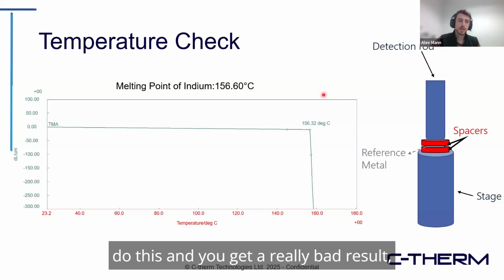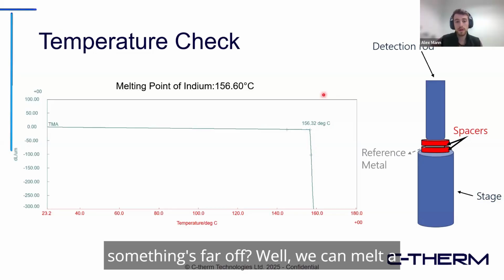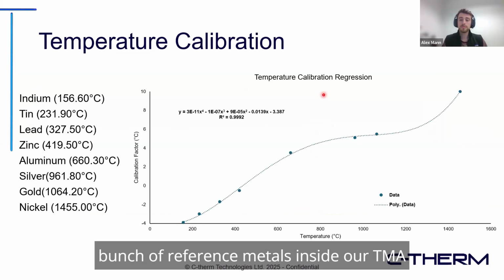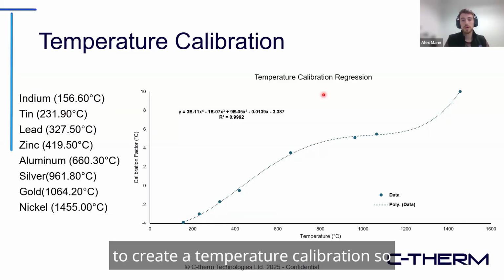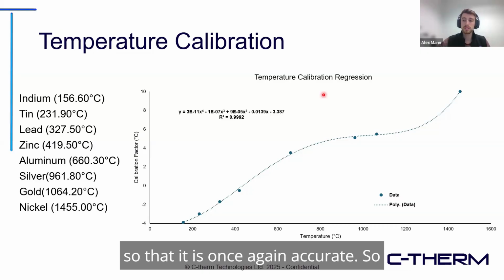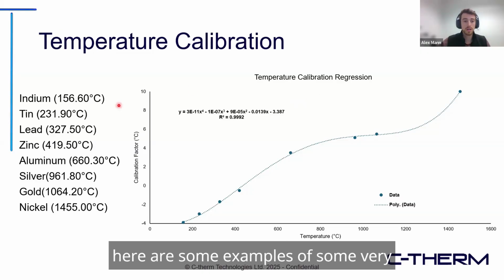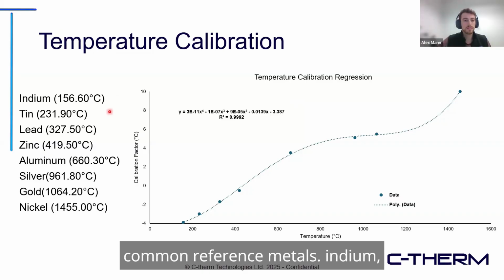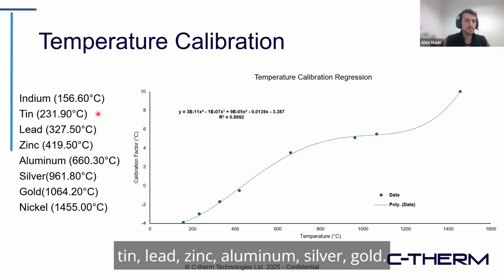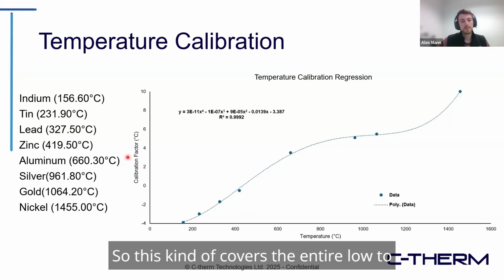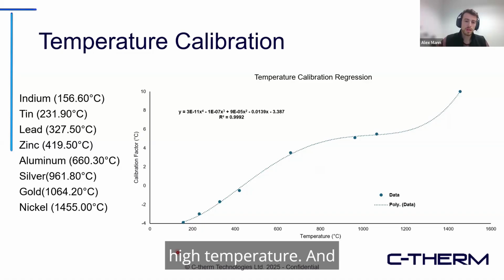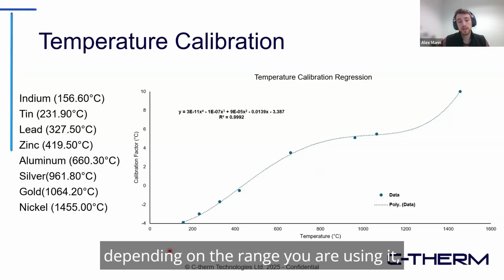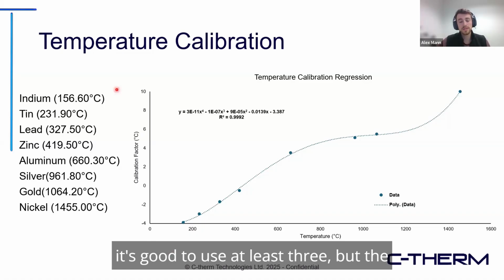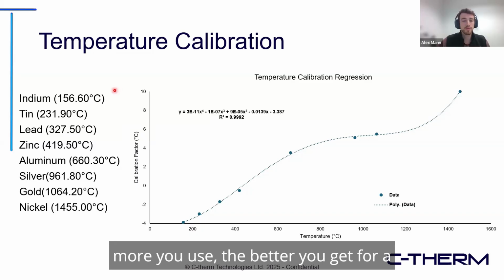Now, what if you do this and you get a really bad result? Something's far off. Well, we can melt a bunch of reference metals inside our TMA to create a temperature calibration so that we can recalibrate the thermocouple so that it is once again accurate. So here are some examples of some very common reference metals: indium, tin, lead, zinc, aluminum, silver, gold. So this kind of covers the entire low to high temperature range. And depending on the range you are using, it's good to use at least 3, but the more you use, the better curve you get.